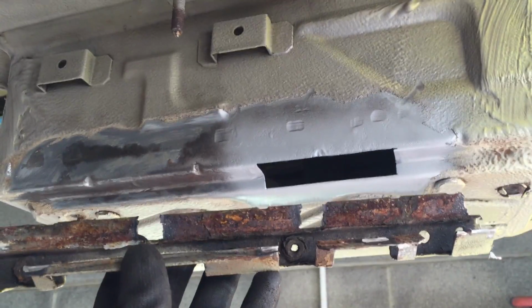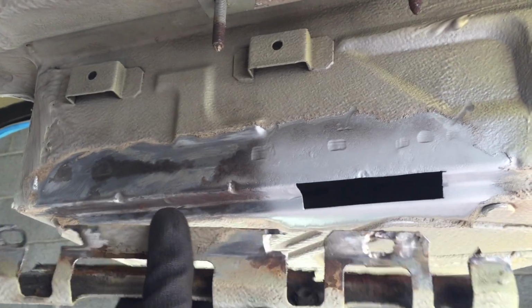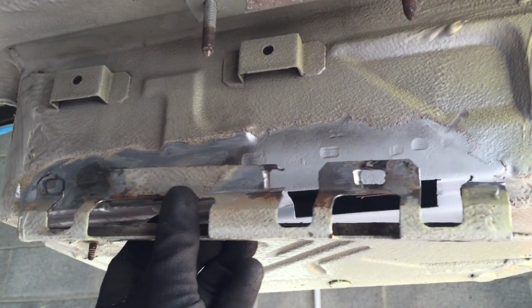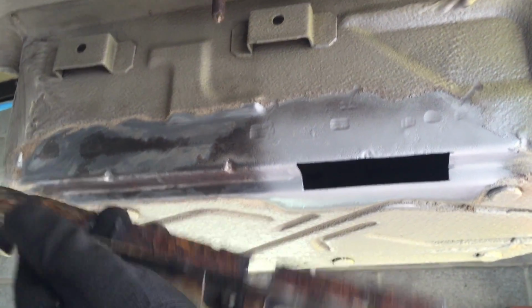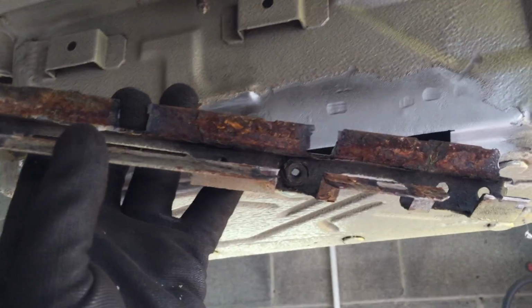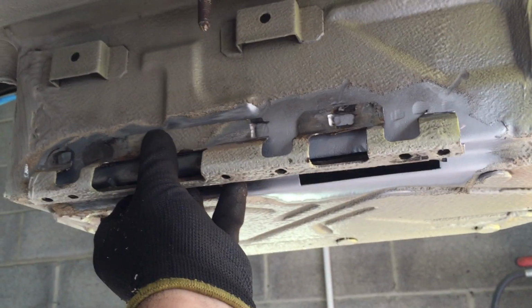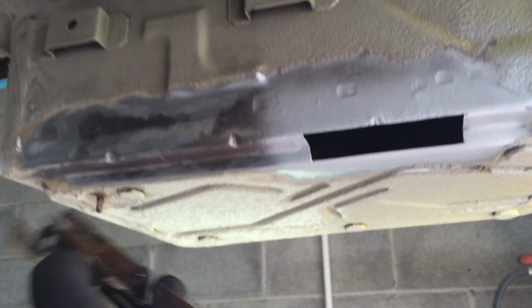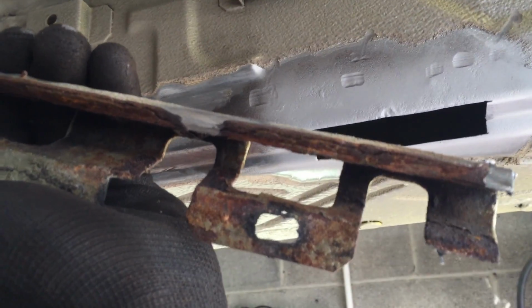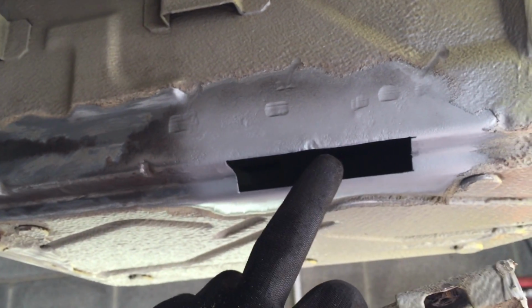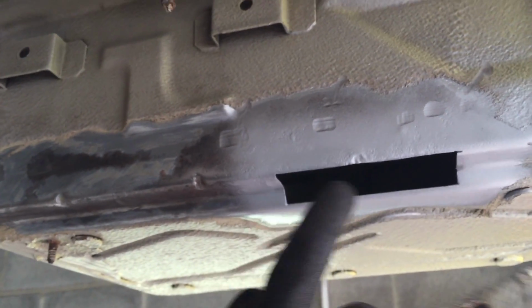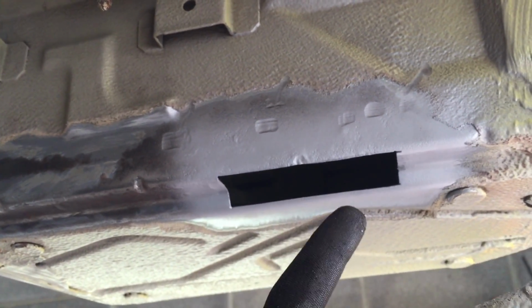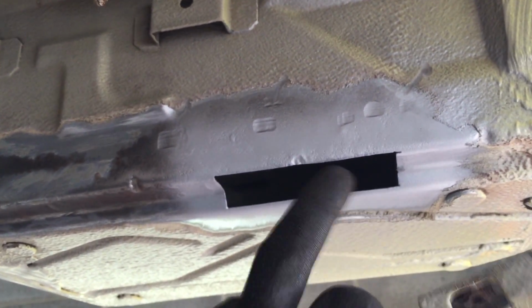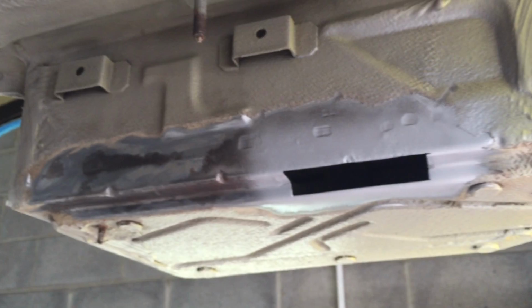So we removed the battery tray redundant bracket on this M3, and we like to take these off because they're a massive corrosion trap. As you see, all the corrosion on the back of this bracket looked quite good when it was on the car and you'd never be able to get to it. It's quite layered, this corrosion, and it had actually made a hole under here, so we cut a section out that's affected, made a repair panel, got it in weld through primer, and I'm just about to get that welded in now to repair the battery box tray.